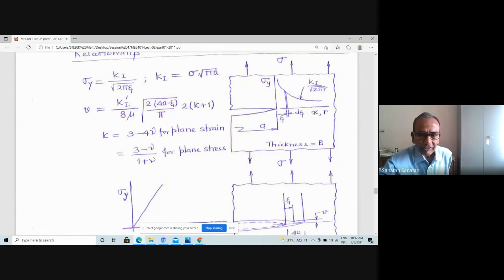And when we try to have sigma, then this R has its coordinate origin at the crack tip. So if we try to see the variation of the stress acting in the y direction, sigma y stress on the crack line, it varies like K1 by root 2 pi R. So it's a square root variation. As distance increases, it reduces, and at R equal to 0, stress is infinity. You see that at the crack tip, stress is infinity.